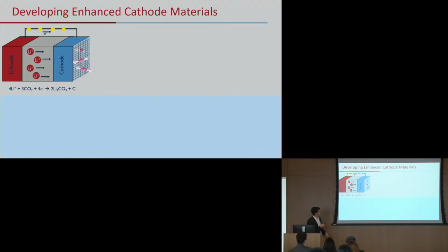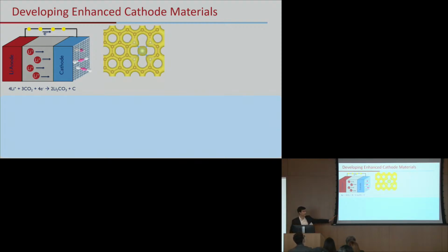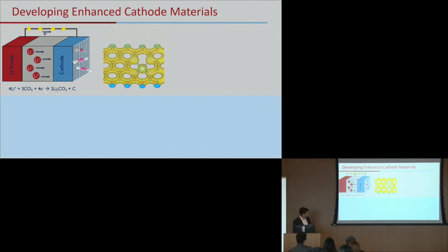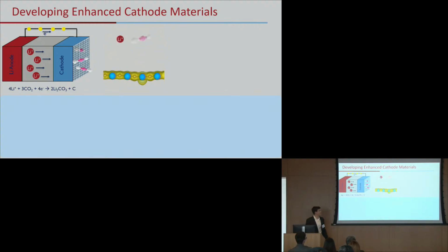And if you look specifically at the catalyst we're using, we can see the electronic structure there. It's graphene with transition metal and nitrogen moieties in there. And we see reactions happen on this catalyst, interactions with lithium and the carbon dioxide that are coming in. And we can see different steps of our reaction mechanism, like a discharge and charge reaction mechanism. And we can even add things like ligands and other additives to the cathode environment to see how we can change what other papers presented, which is iron and nitrogen moieties. How can we change that? How can we make a better cathode material?